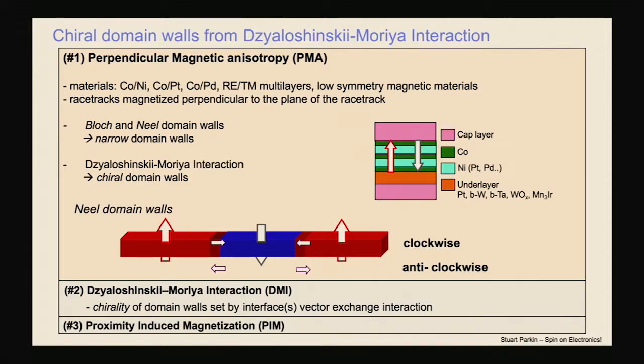So this Dzyaloshinskii-Moriya interaction at interfaces, which was first observed using spin-polarized tunneling in Wiesendanger's lab many years ago, has now proven to be critically important for racetrack memory. By these chiral domain walls, they can be moved with current much more efficiently than using, for example, torques from currents polarized within the magnetic layers.